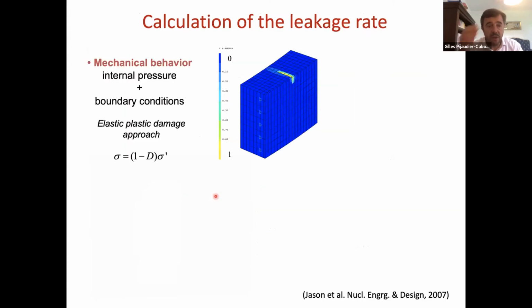What is currently done is first a mechanical calculation. Due to the internal pressure and the boundary conditions, you get some mechanical model - here it's an elastic plastic damage model - and you calculate the damage, the effect of damage resulting from the internal pressure on the vessel.